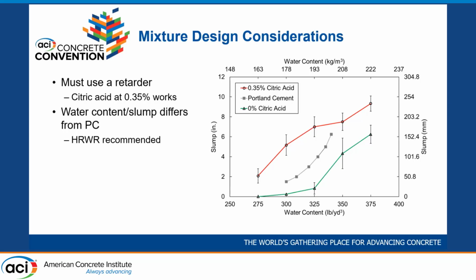That's good for about 45 minutes of working time. And then if we increase citric acid dosage from there, we still get some additional slump benefit. So it's quite different from Portland cement in terms of slump. You can see that these curves are concave down instead of that concave up relationship in ACI 211.